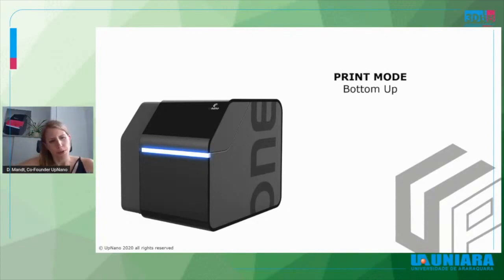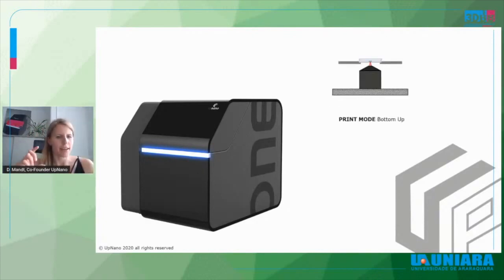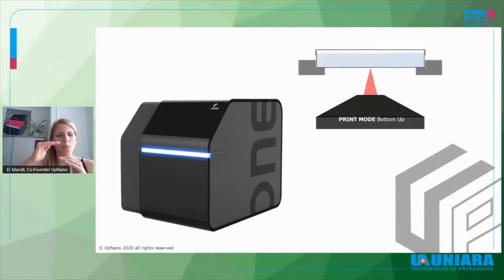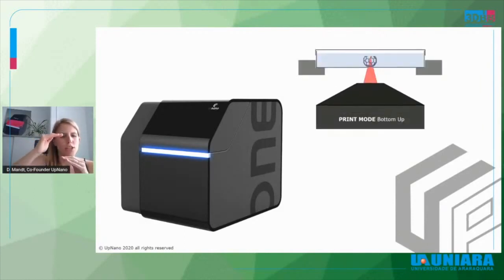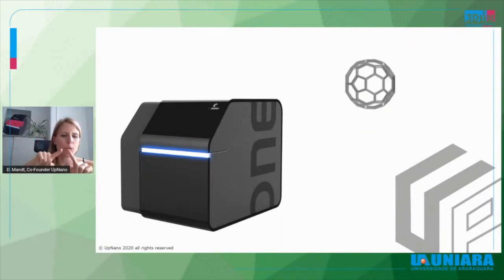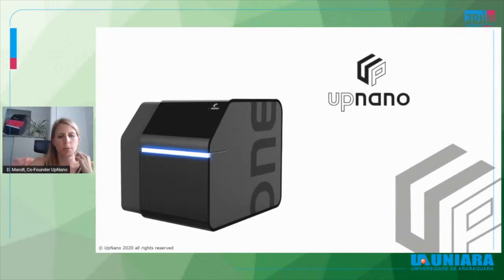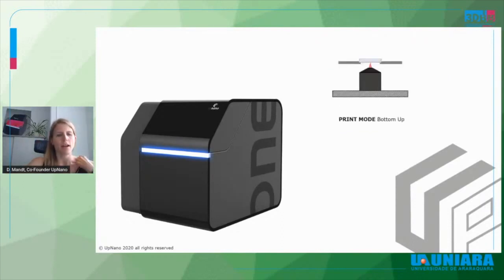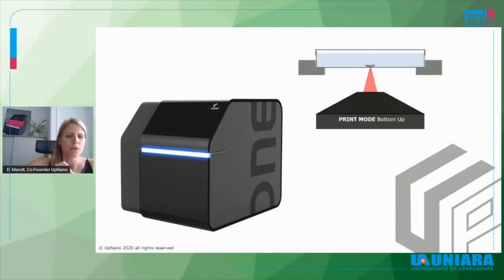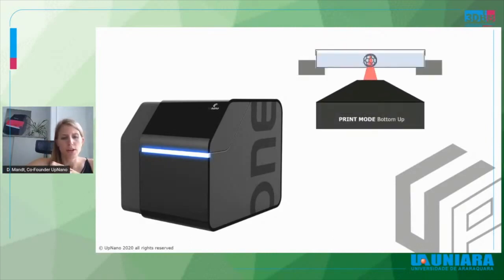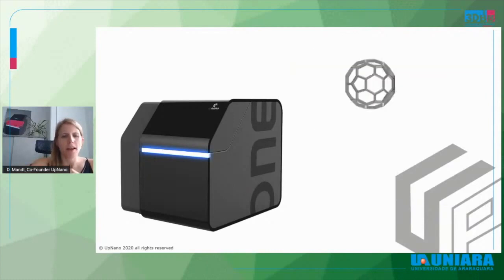This printing process is limited to a certain height. As you can see here, when the laser is reaching the top, the laser beam always focuses through a polymer which was already hardened. And this can lead to artifacts and reflections. And therefore, your parts are not true to geometry anymore. But we have a solution for that problem.